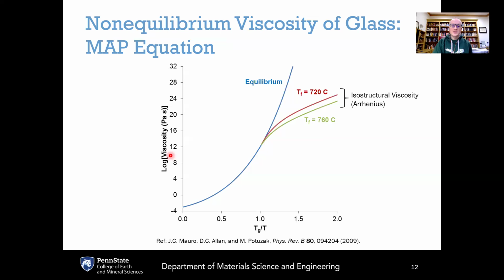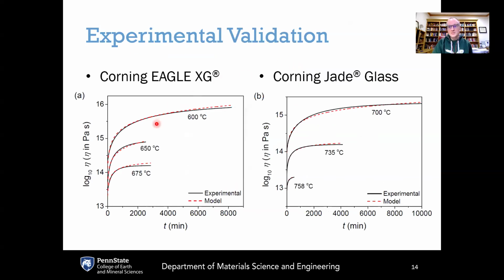The reason that it's increasing over time is that if you take the glass here and hold it at a constant temperature, over time it is continuously trying to relax towards the equilibrium liquid. And as it relaxes towards the equilibrium, it is moving upward vertically from either the green or the red curve here toward the blue curve. And as it moves upward, the viscosity is increasing. This is a spontaneous process as the glass relaxes and tries to reach something closer to a thermodynamic equilibrium. That involves the viscosity increasing on a logarithmic scale. So this is increasing by orders of magnitude.